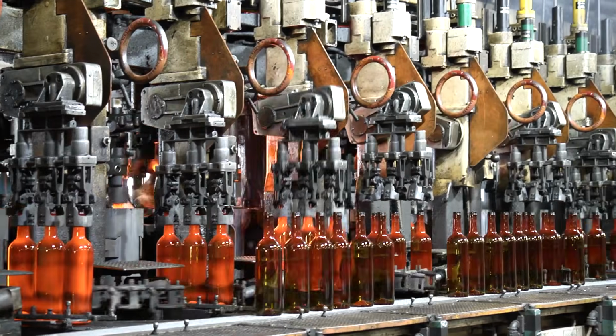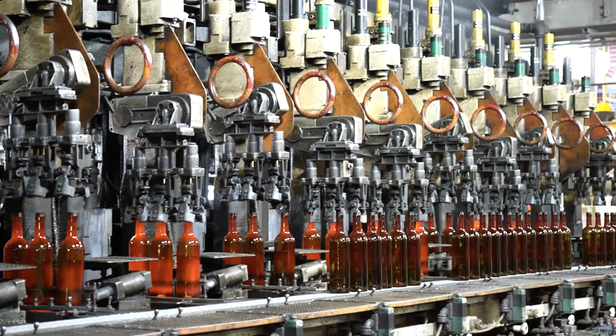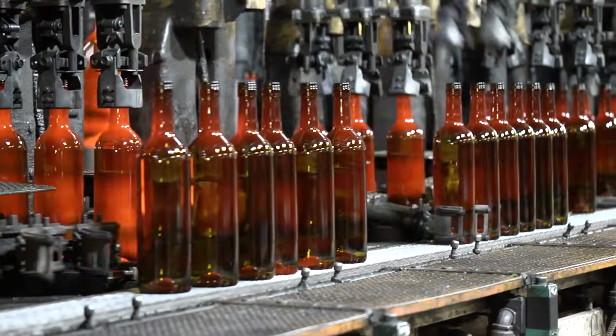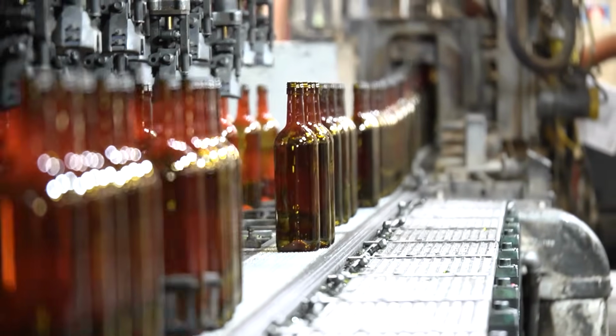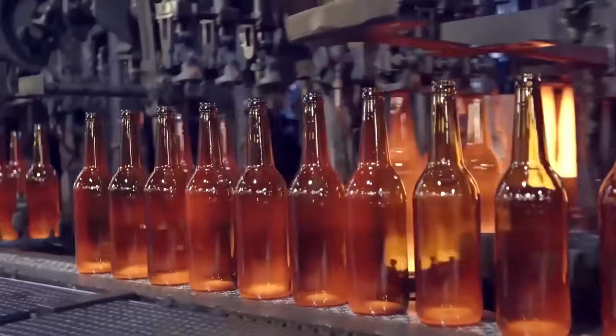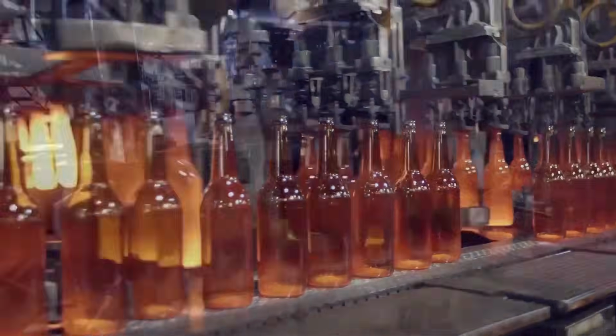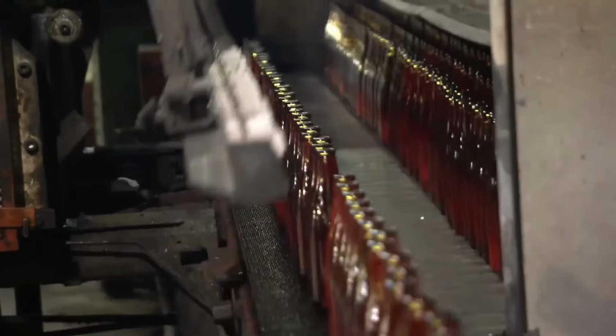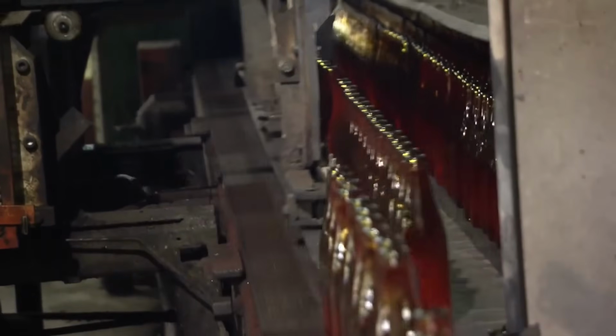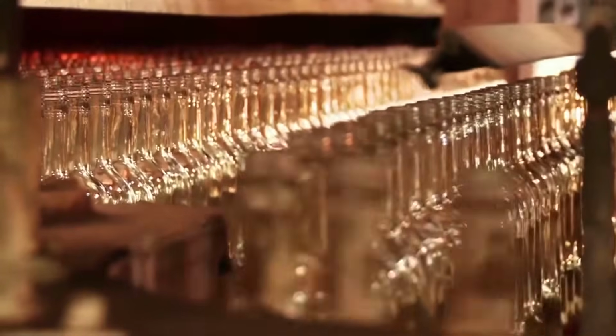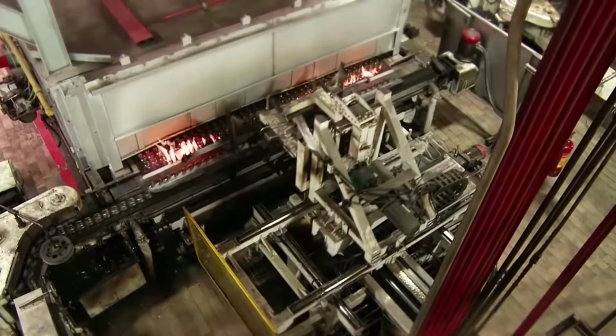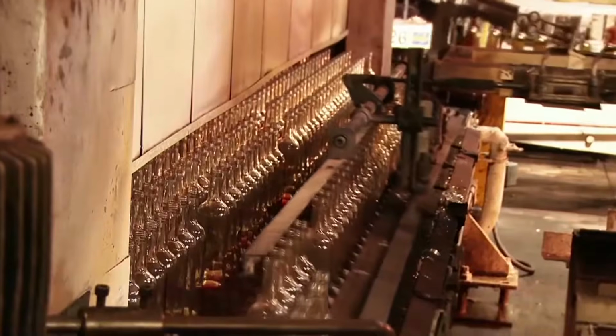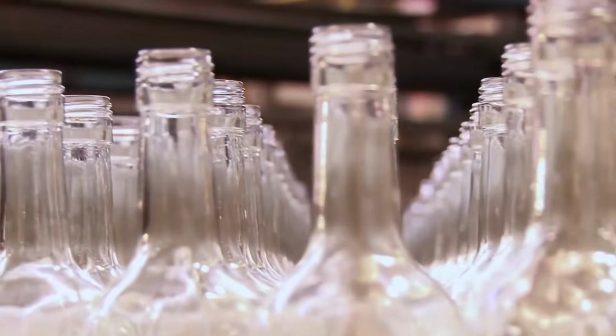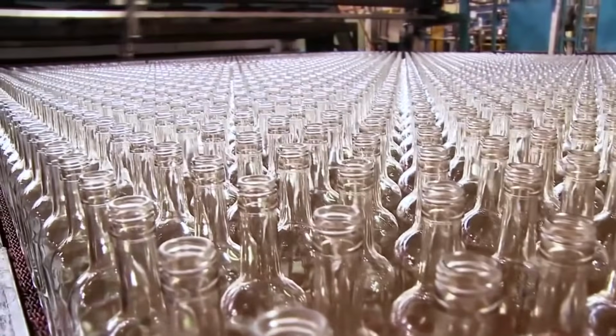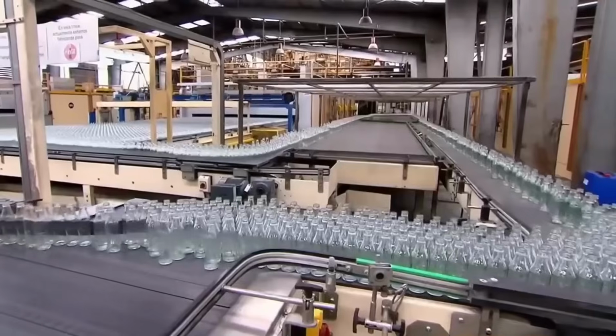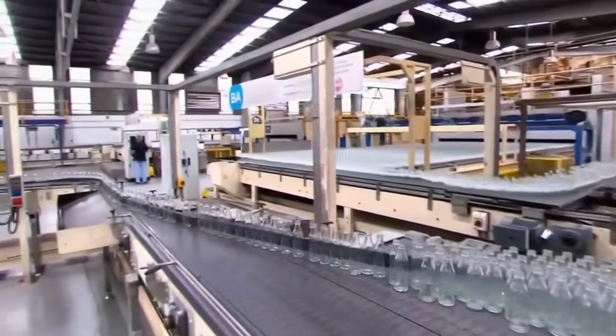When bottles exit the molds, they appear solid. They are not. A sudden temperature change could cause them to shatter. To prevent this, they move along heated conveyors that keep thermal conditions stable. The system cannot tolerate abrupt cooling. The bottles enter the annealing tunnel still glowing at nearly 600 degrees Celsius. Inside, they cool slowly for over an hour. This controlled cooling releases internal stresses created during forming. If this step fails, bottles can crack hours or even days later, sometimes after they are already filled.